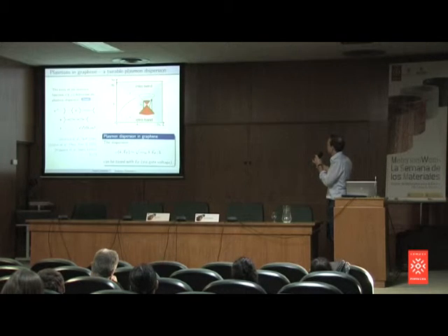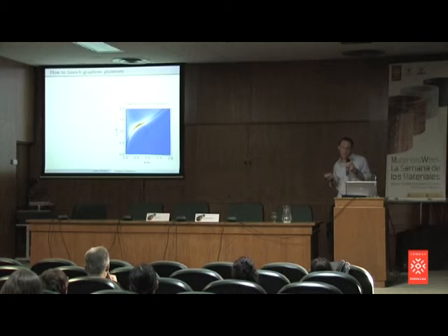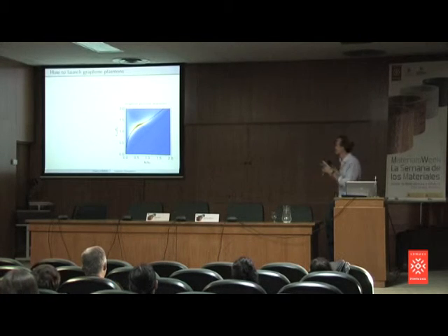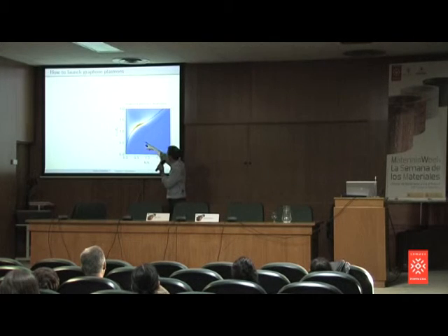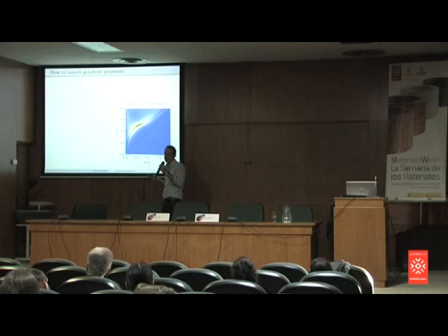Good. Now, I haven't told you yet how you actually get graphene plasmons. How do you excite them? I just told you it's an oscillation of charges, yes, but how do you make this? Shine light on it, approximately, yes. But it won't work so easy because the problem is, again, here you have the dispersion now of the graphene plasmon. And this diagonal line here in this plot, this is the band of the graphene electrons. That means the diagonal line here is k vector times Fermi velocity.